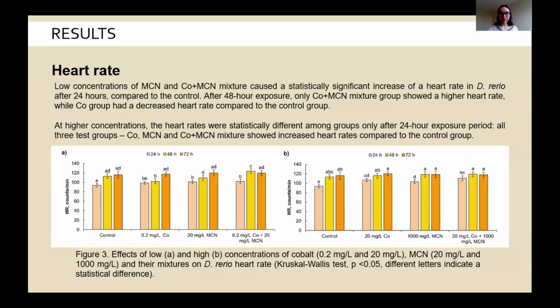We also checked the heart rates. Here on the left, you can see heart rates of Danio rerio at different time points after exposure, so 24, 48, and 72 hours. What we noticed is that at low concentrations, MCN and the cobalt plus MCN mixture caused a statistically significant increase of the heart rate in Danio rerio after 24 hours compared to the control. But after 48-hour exposure, only the cobalt plus MCN mixture group showed a higher heart rate, while the cobalt group had a decreased heart rate compared to the control group. And after 72 hours of exposure, there were no more statistical differences.